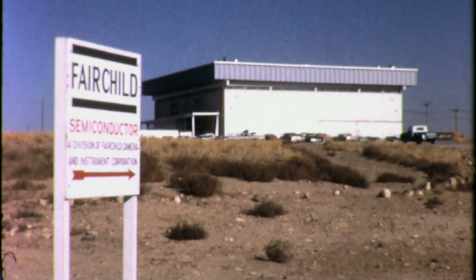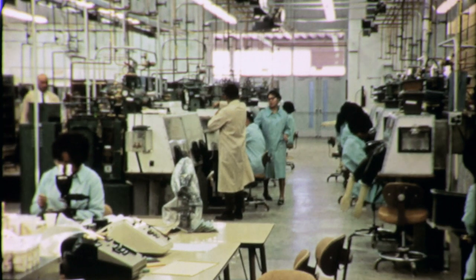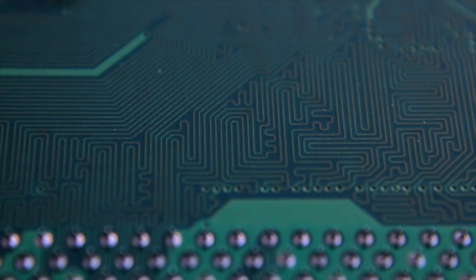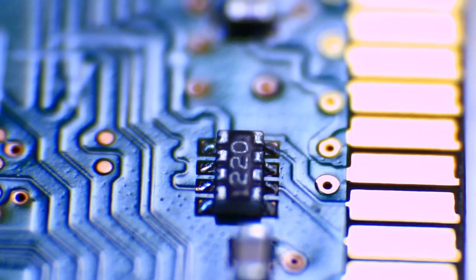Basically, without plasmas, the semiconductor industry wouldn't exist. Plasma processes are used to fabricate the components that make up microchips. In the 70s and early 80s when there was no plasma, they were limited in how close they could fit features together, because the chemical processes would etch right and left in addition to down, so you could not have features spaced close together. The gigascale integration is only possible with plasma processing — that means spacing things tens of atoms apart.